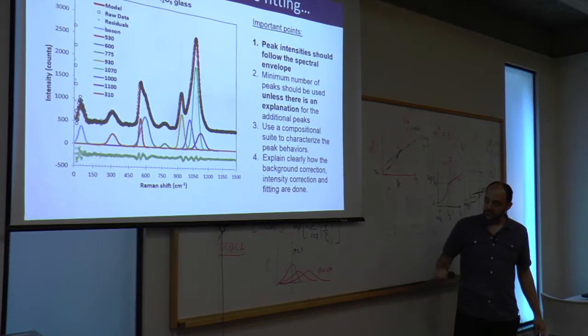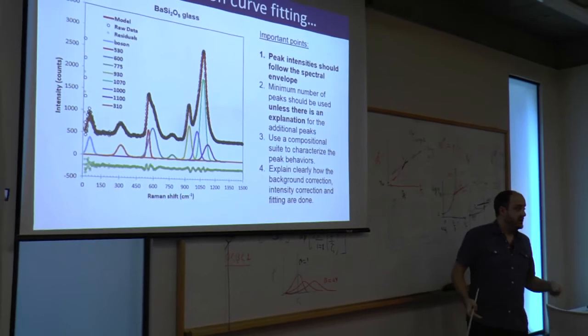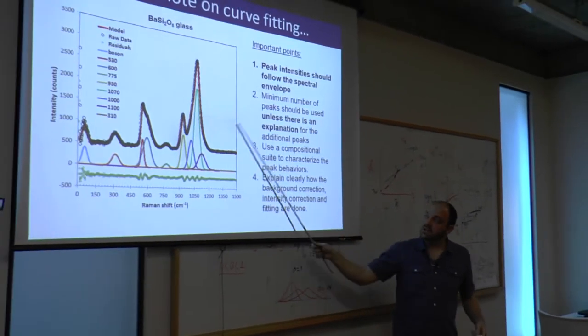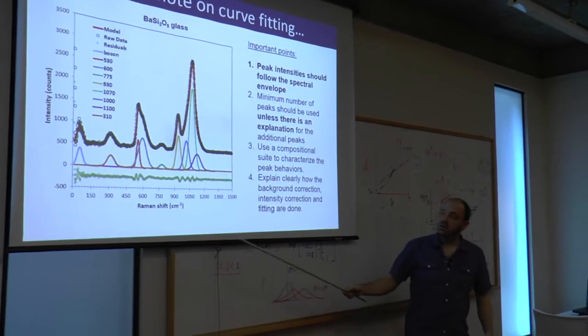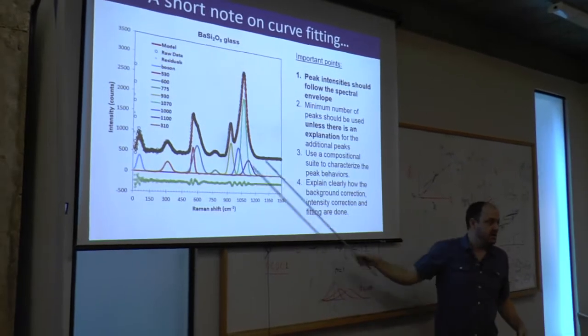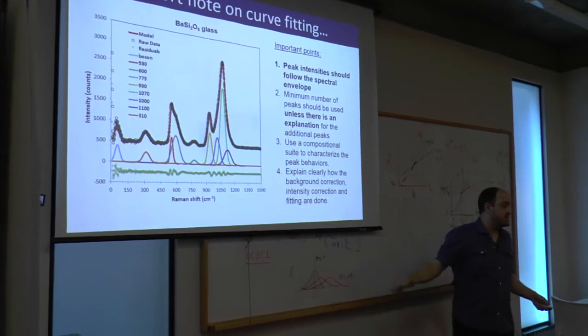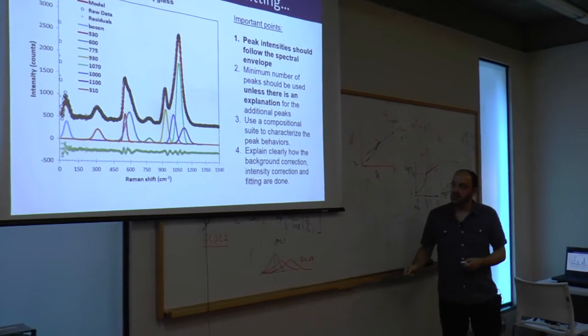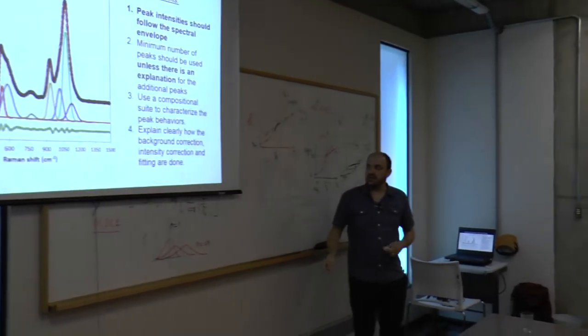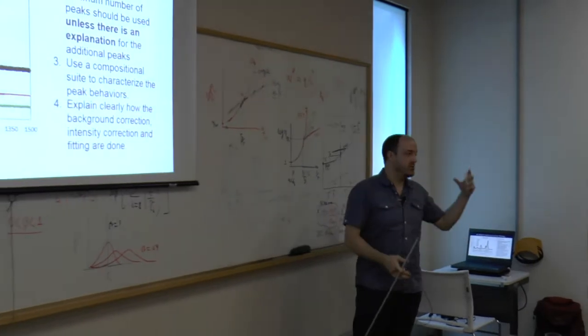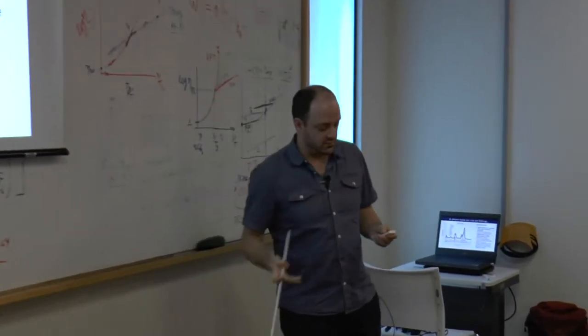fitting. Explain the intensity correction, and you might do an intensity normalization when you show the whole spectra, but when you just look at the QN species, you'll probably area normalize it to get the proportions of the QN species. So explain exactly how you've modified the spectra from the raw data to get your structural model.